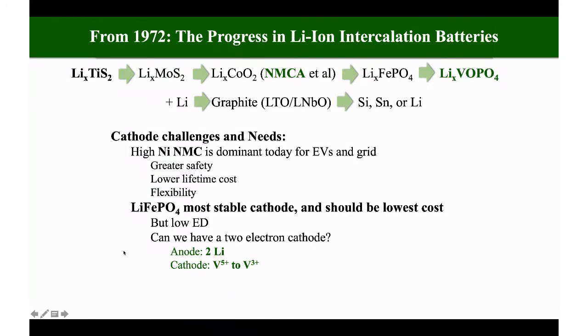I've already described that lithium iron phosphate is the most stable cathode. It should be the lowest cost. I'm not sure it is right now, but it's much lower energy density. Hence the desire to put 2 electrons or 2 lithium ions into this structure. We've tried this with iron. It doesn't work because the redox potential of iron is about 5 volts, and that decomposes the electrolytes.